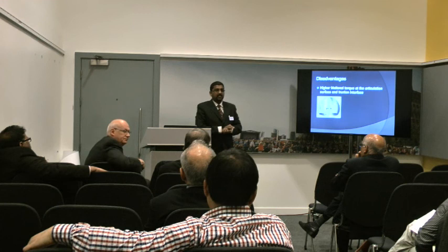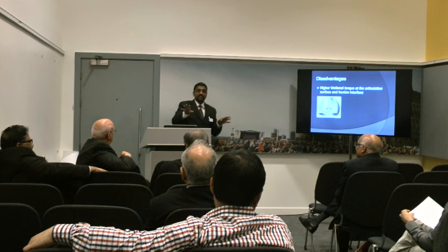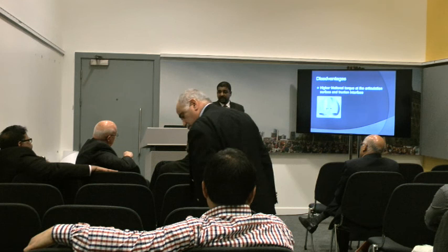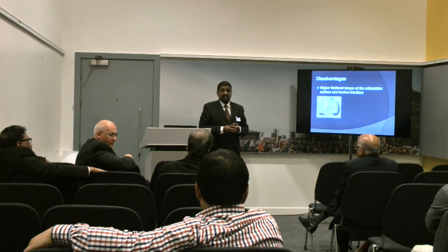So unlike a metal on metal articulation, I don't think we will be able to find it out. You think this was not jammed in properly? No, it's a figure of speech. For example, in those case reports where trunnion related wear led to revision, there are various possibilities. In fact, one study showed that even a drop of blood in the trunnion before the head is seated can increase the wear due to oxidation, quite substantially. But these are in vitro studies. Multiple factors can amount to this problem. Even a patient's allergic reaction to the smallest debris can also cause it. So I guess there is no real answer to that question.